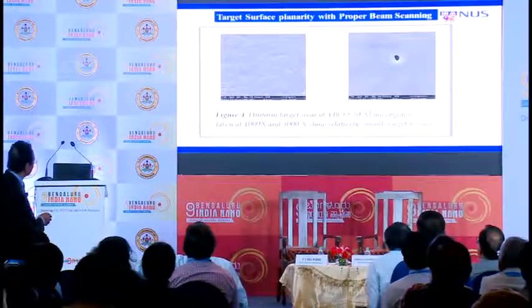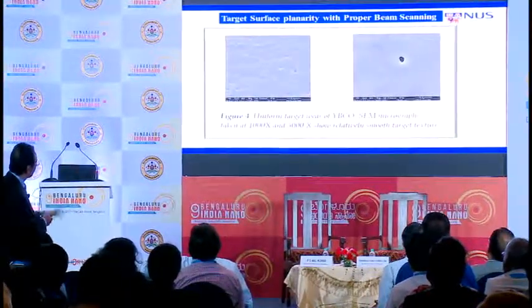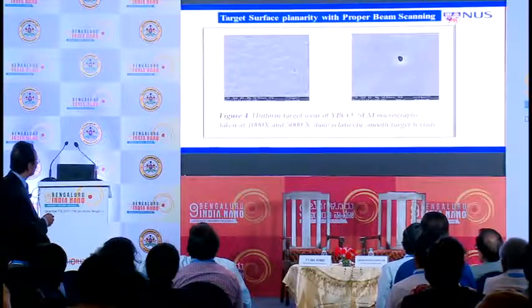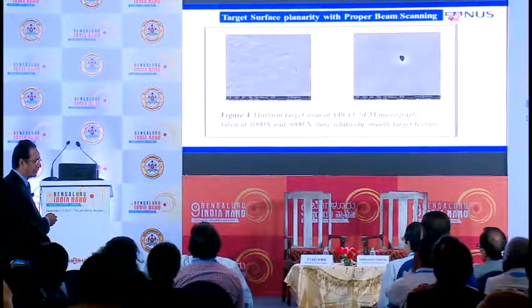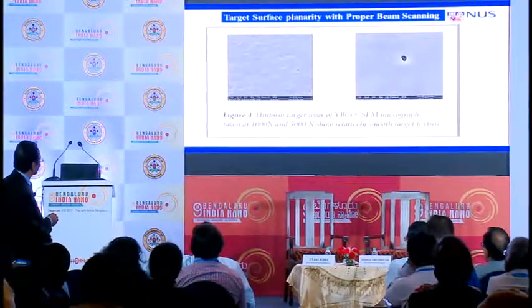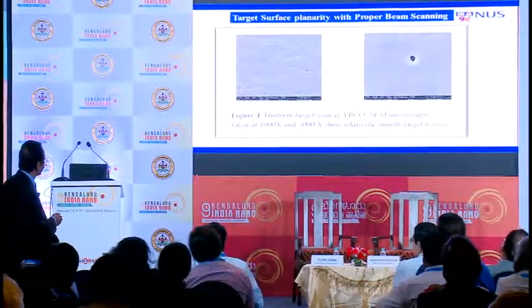And once we do that, essentially the target looks like this. Ultra smooth, very, very thin. The target looks like a mirror. So you don't have to polish that, and the film comes out with very thin particles.